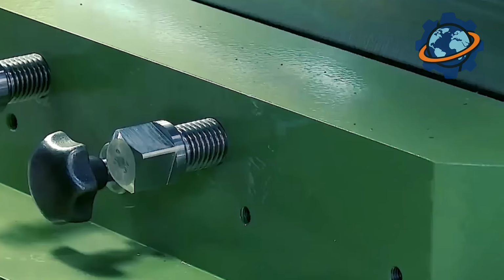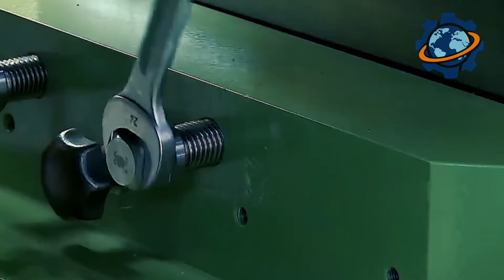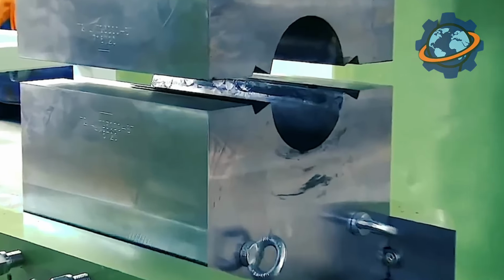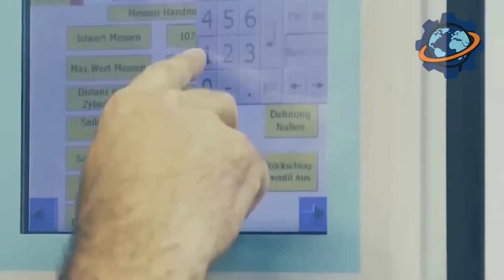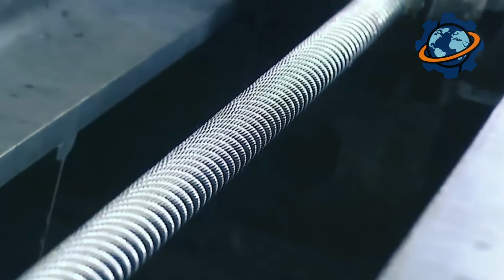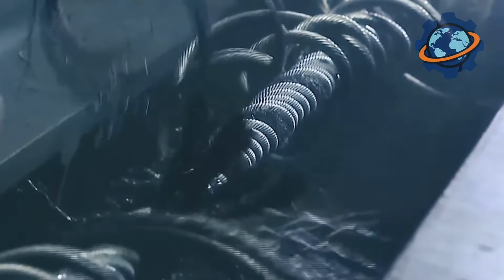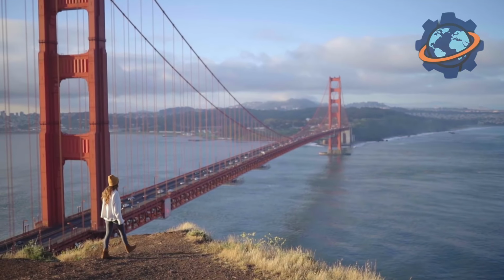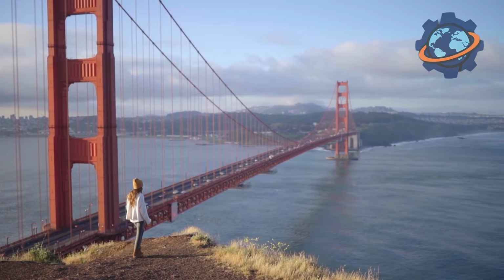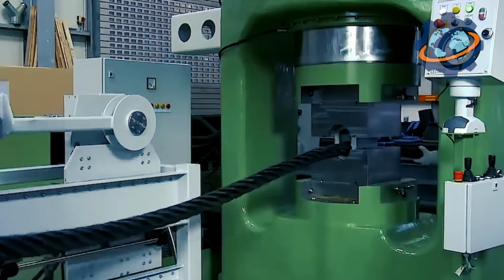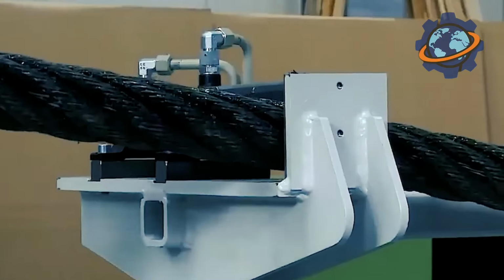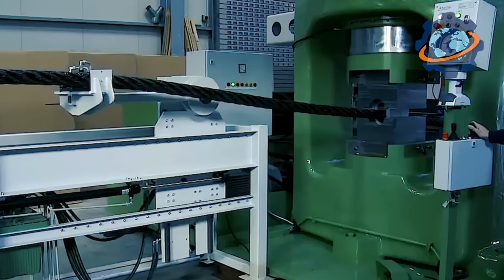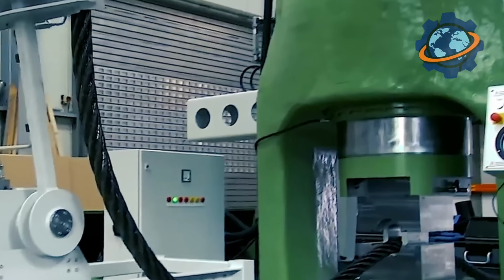A portion of the batch is selected for mechanical testing. The wire is clamped in hydraulic jaws and pulled until it breaks. This determines its tensile strength and breaking load. If the wire holds up, it's ready for work at heights of hundreds of feet, supporting the weight of cars on a bridge. The surface is checked separately for micro cracks, burrs, corrosion. High-resolution cameras or even eddy current testing are used here, which can see beneath the top layer of metal.